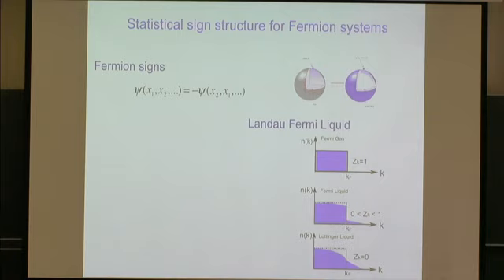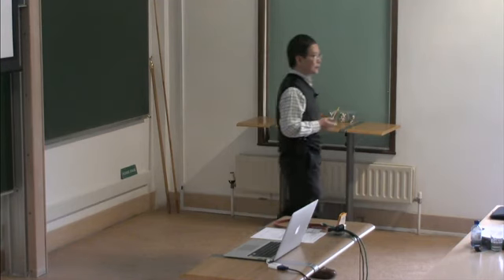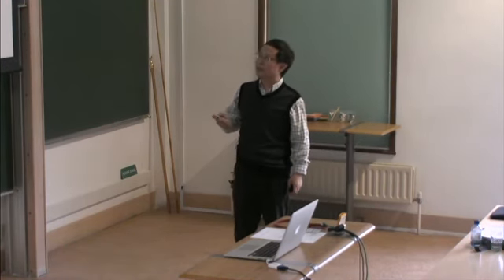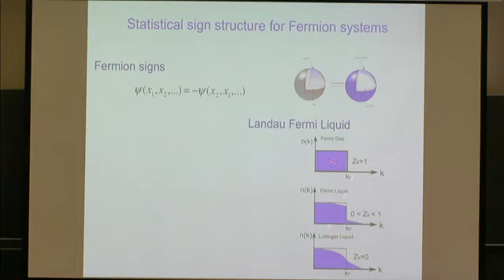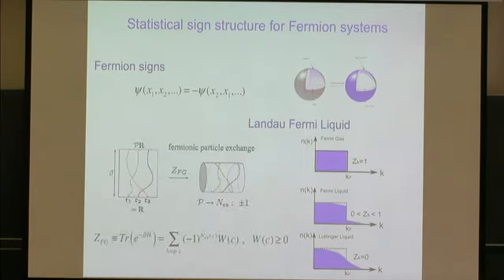That's the weakly interacting case, where we know there's a fermion sign in the non-interacting fermion system. The wave function for identical particles will change sign under the switch of coordinates of identical particles. Then you have this for the Fermi gas case, as I mentioned earlier. Turning on interaction will reduce the quasi-particle weight, and if you formulate things in path integral, in imaginary time, the partition function can be written in such a form where any switching of two identical particles will give you a minus sign here, and it just keeps track of the exchange between particles.